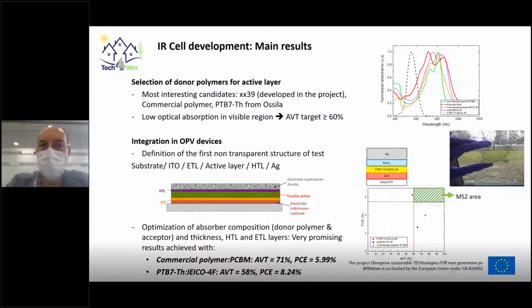At this moment, we have had a very strong activity in the identification of the donor polymers for the active layer. We need a very high transparency level, so the polymers have to have absorption essentially in the infrared region. Here you can see in the transparency the normalized absorbance versus wavelength of the most optimal polymers that have been identified in the project. In black, you can see the eye sensitivity, which is essentially centered in the green spectral region of the visible region.